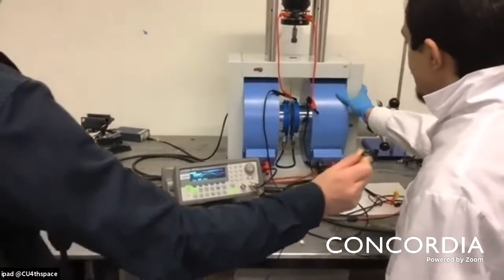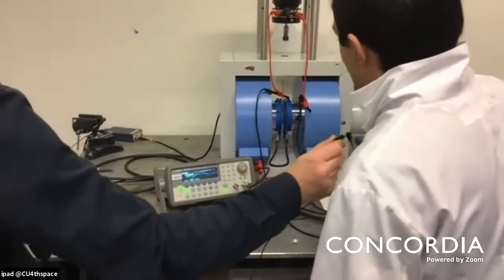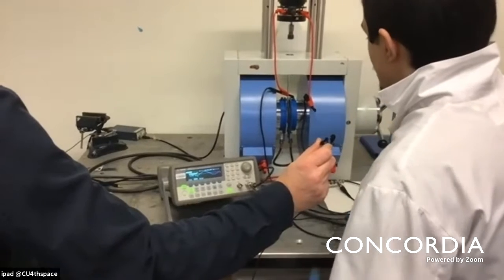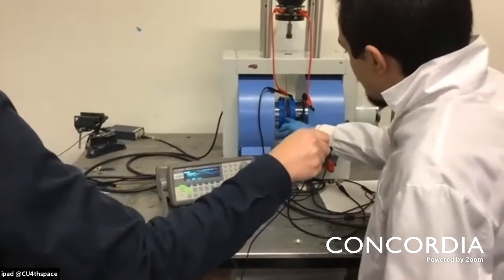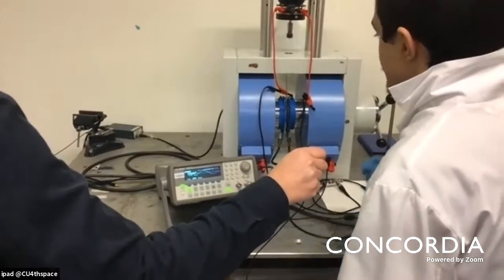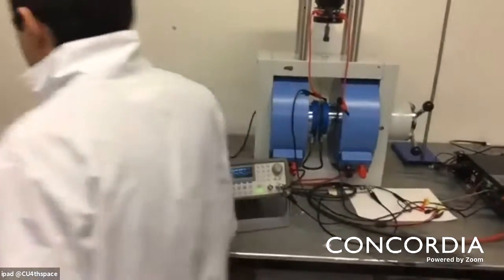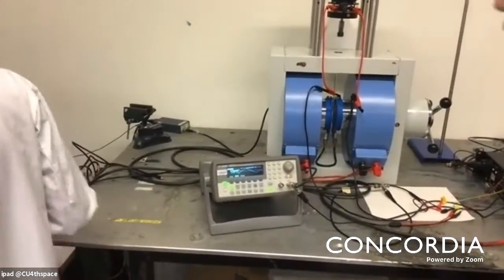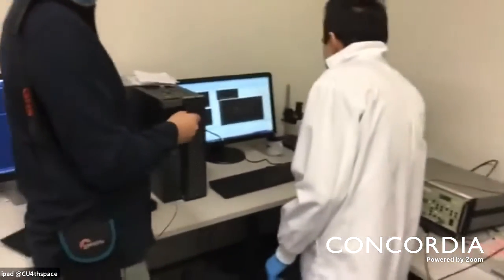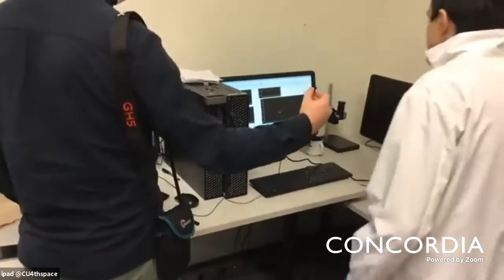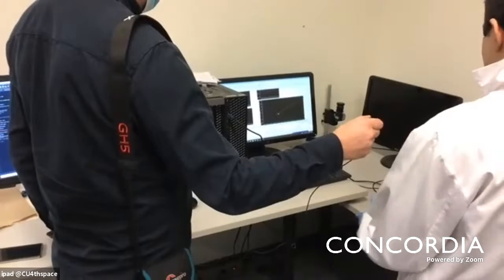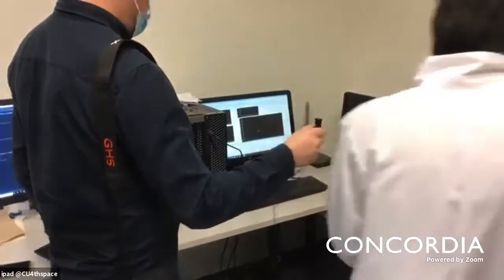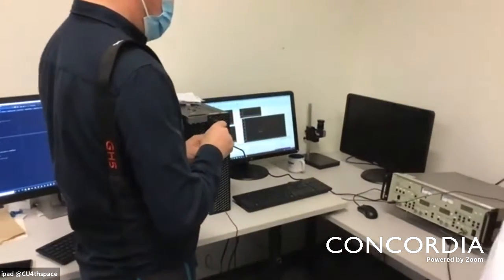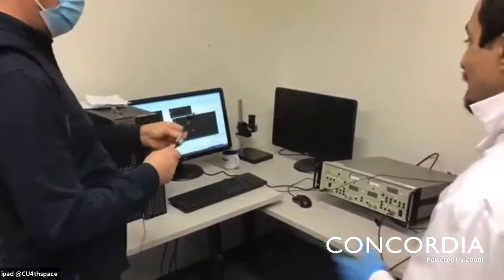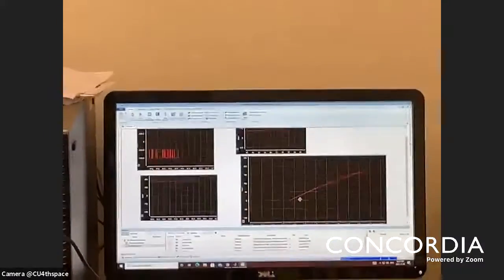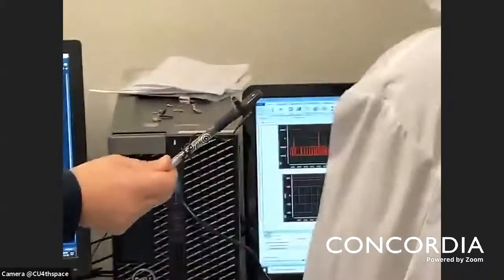This is a coil that applies a perpendicular magnetic field to the object. With this movement, a current or EMF will be induced in the pickup coils that I designed for this device. And this amplifier can measure the amount of the current or the voltage. Based on the code that I programmed, we can measure the data very easily. It is very important because we can see the behavior of the material under different magnetic fields. For most simulations, you need to define some magnetic properties as parameters in your mathematical model. With this curve, you can extract these parameters.